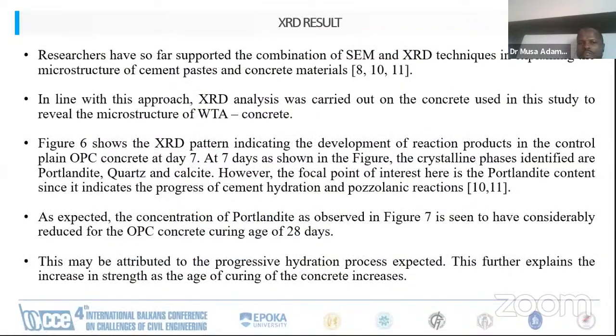Researchers have so far supported the combination of SEM and XRD techniques in explaining the microstructure of cement base. In line with this approach, XRD analysis was carried out on the concrete used for this study. So figure 6 shows the XRD pattern indicating the development of reaction products on the control plain OPC concrete at 7 days. At 7 days, as shown in the figure, the crystalline phases identified are portlandite, quartz, and calcite.